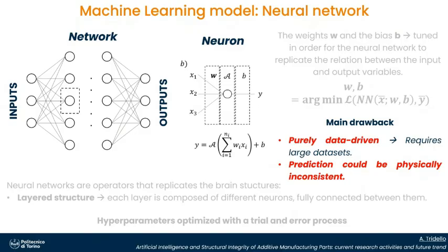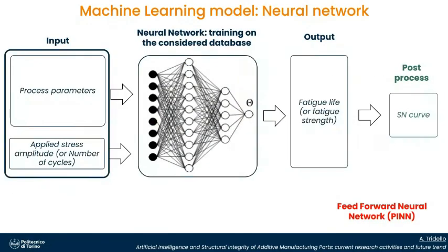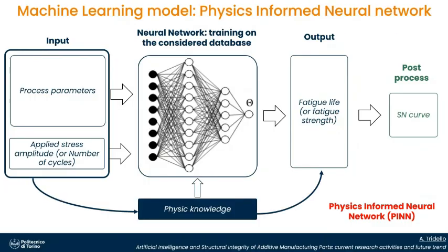Why? Because we must consider that the data have a large scatter in the literature, and so we can obtain some predictions that are not consistent. So this is a quite typical scheme. We have an input, the process parameter, and output, the fatigue response. If we have an input, the applied stress amplitude, we can compute the fatigue life, and then we can obtain the S-N curves as an output. But as I told you, the black box approach has some drawbacks, so we embedded physical knowledge to make the prediction more realistic and more accurate.